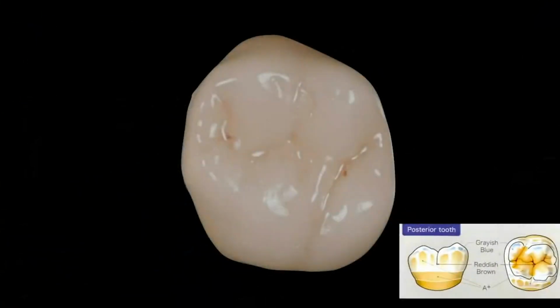So let me just walk you through my process when I'm applying the stain and glaze to a KATANA restoration. So first, after I've done my post-sintered polishing, I'm going to sandblast the surface of the restoration with 30 to 50 micron aluminum oxide. I'm going to sandblast all the surfaces except for the occlusal contact areas. So anything that's going to be occluding against the opposing tooth, that area I'm not going to sandblast. And then I will clean it with steam cleaner or alcohol, and then apply a thin coat of the clear glaze liquid. And from there, I will coat the crown with a layer of the glaze.